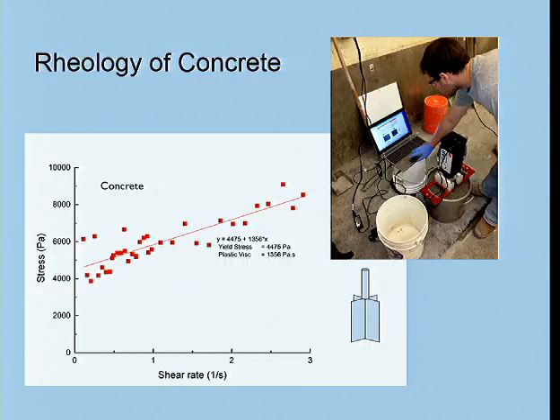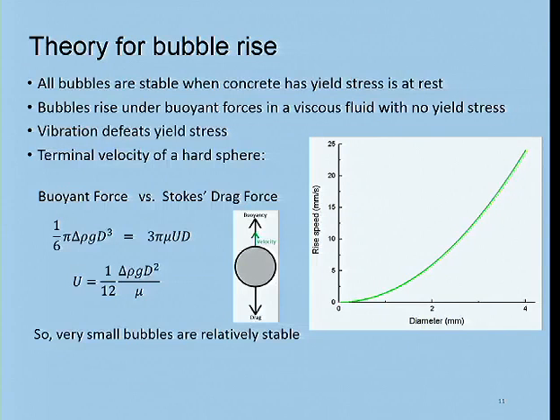So here's a picture of how we measure rheology of concrete, and this is some data that shows this kind of Bingham behavior, and we have little tools in the lab that allow us to measure rheological properties on bulk concrete samples. The theory for bubble rise goes something like this: if we have a bubble that's hollow inside, there's a buoyancy factor, and it's going to be counteracted by Stokes' drag force.